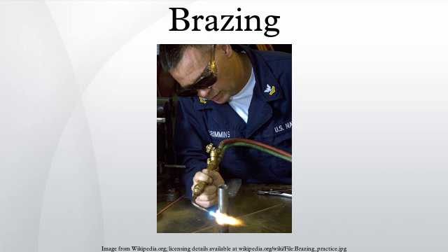Combusted fuel gas: 73 to 75% N2, 10 to 11% CO, 15 to 16% H2. For copper, silver, copper phosphorus and copper zinc filler metals. For brazing copper, brass, low nickel alloys, Monel, medium and high carbon steels.